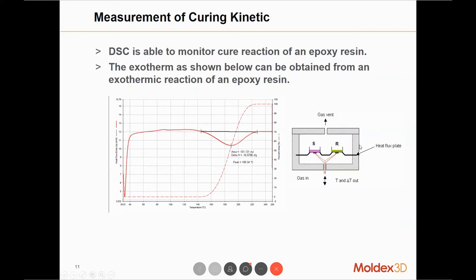So we'll have a heat flux plate, and at the same time record not just the temperature change, but also the heat flow. As you can see on this graph, at the beginning stage of the heating, the temperature of the polymer will increase under a constant heat flow, but once the material starts to cure, as you can see on this line, this means the curing has started. Once curing starts, the heat flow will decrease as the chemical reaction is taking place.